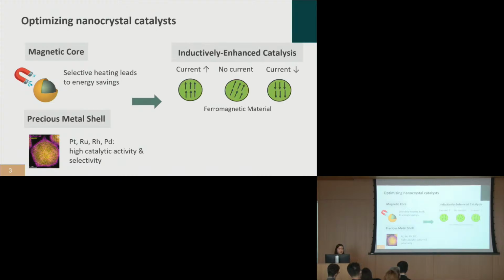So I'm applying this to a system called inductively enhanced catalysis, where we flow an alternating current around a whole system of nanoparticles, and that allows them to generate heat from the inside out. The nanoparticles can then use most of the heat that they generate all by themselves instead of an external heat source. And this is just one example of the results that we've obtained.